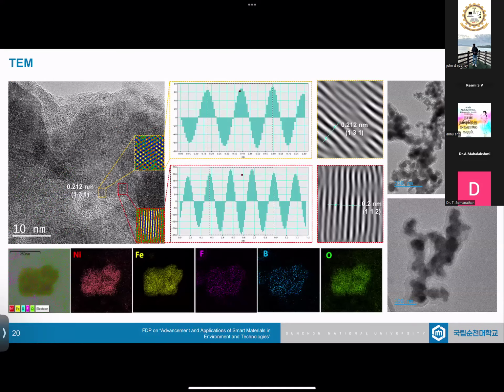So we moved further. The TEM also confirms it: the TEM-based SEM mode EDAX color mapping was again done, and we found that the presence of fluorine is still there, which is confirmed in TEM also. The plane indexing and all the things which we usually do, we compare it with XRD and try to understand. This confirmed that the phase formation is proper, but still this was bugging us a lot.